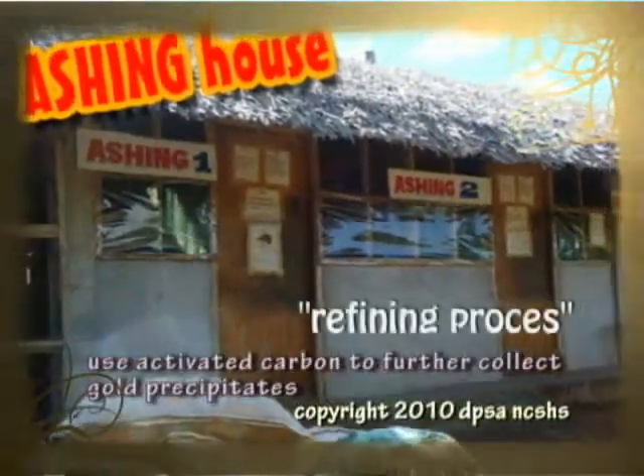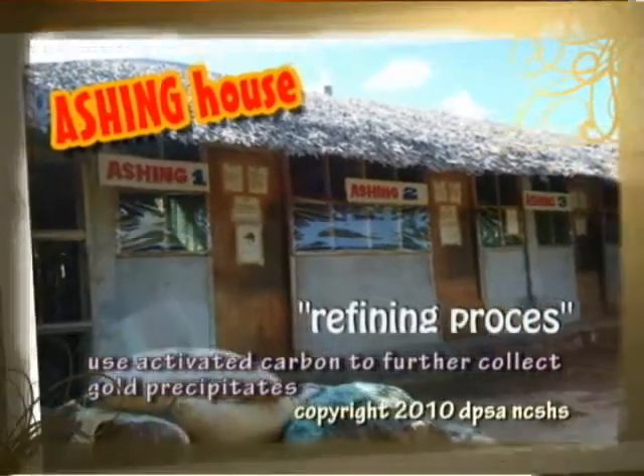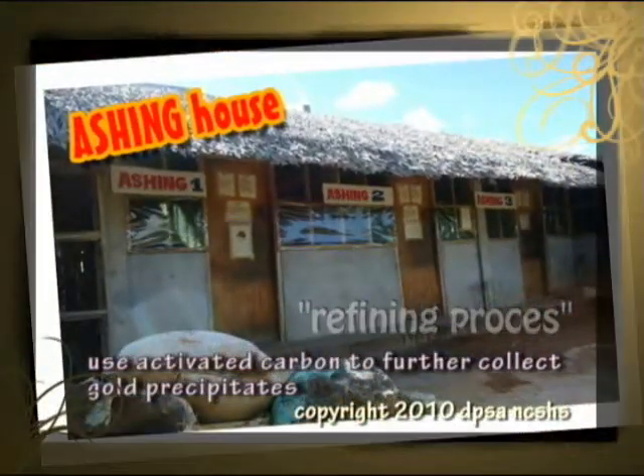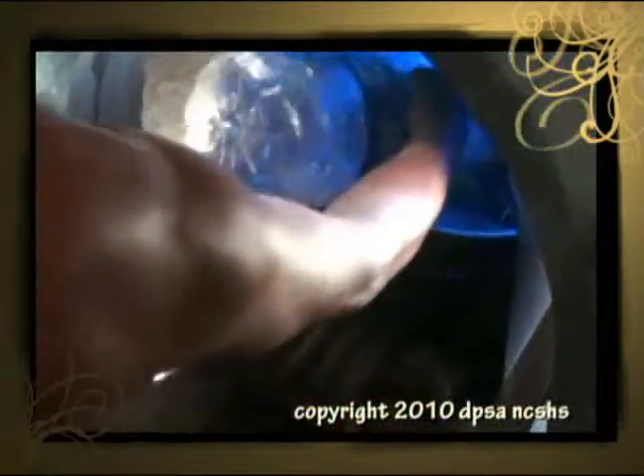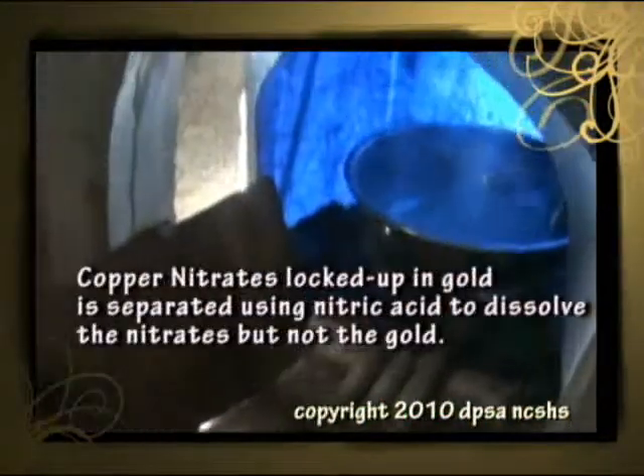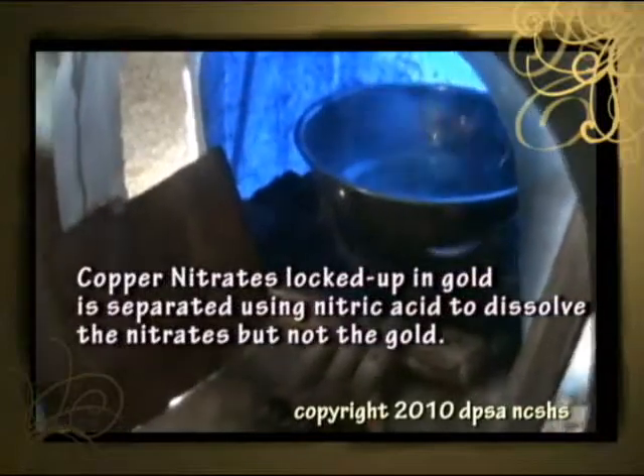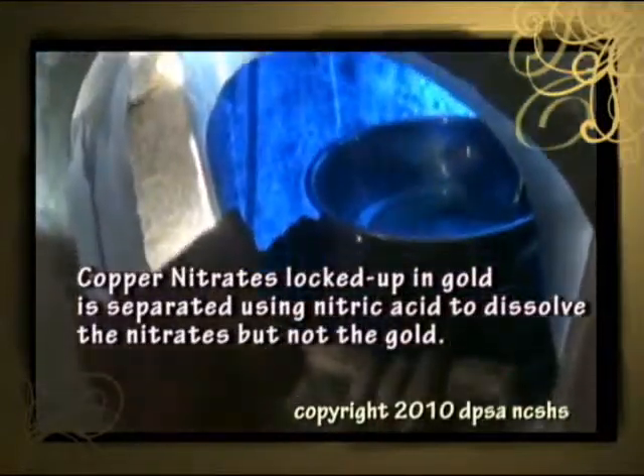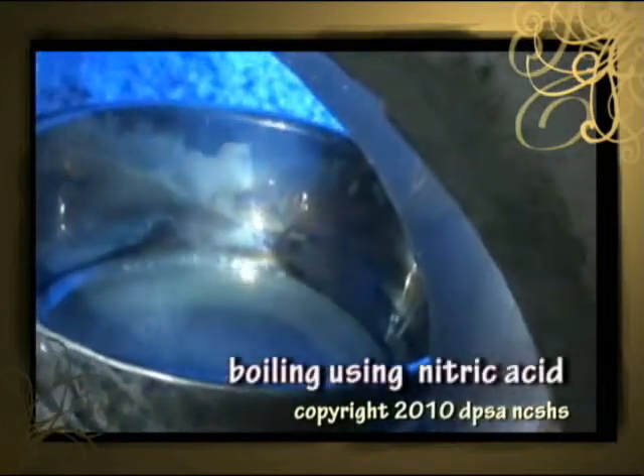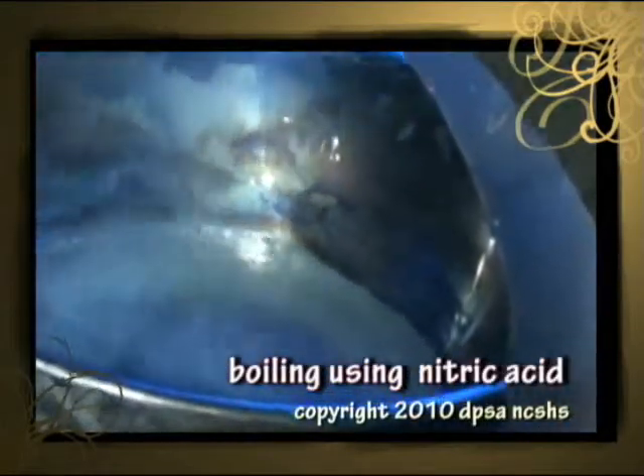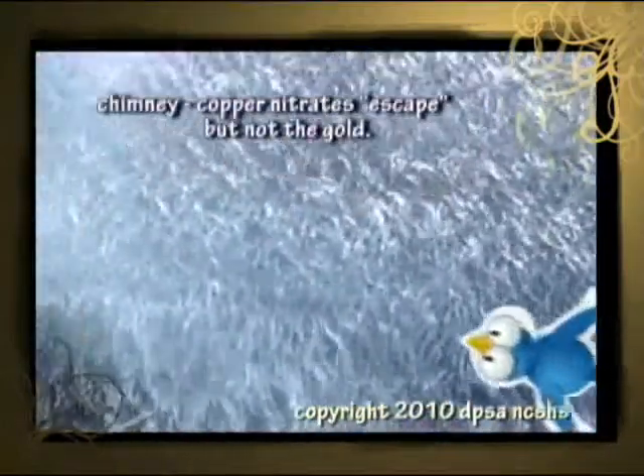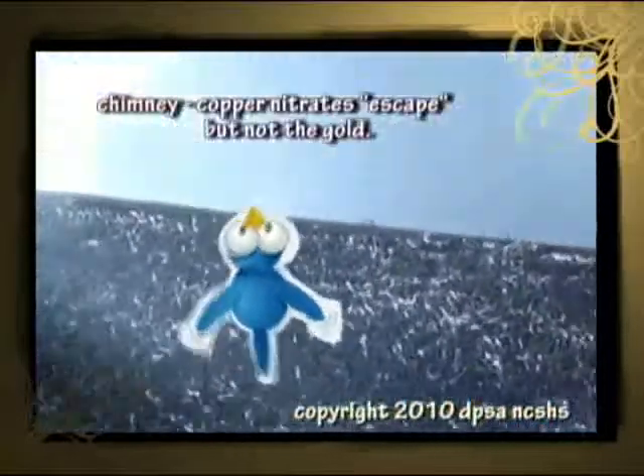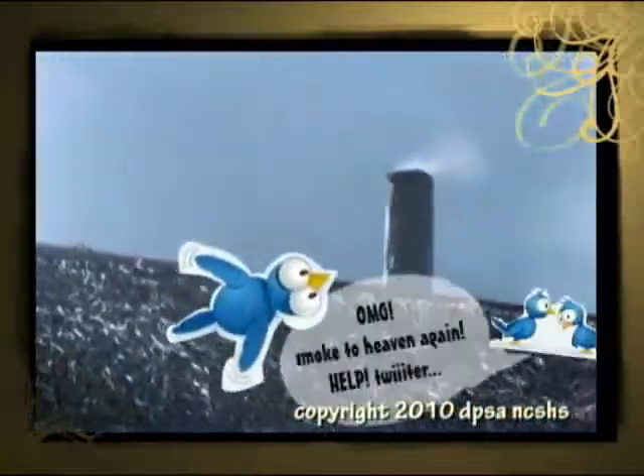The collected gold particles will undergo the refining process conducted in the ashing house, where activated carbon is used to further collect gold precipitates. Further refining is done where the copper nitrates that are locked up in gold are separated using nitric acid to dissolve the nitrates but not the gold. Boiling the gold-laden solution using nitric acid. However, the nitric acid vapor escapes at the chimney.